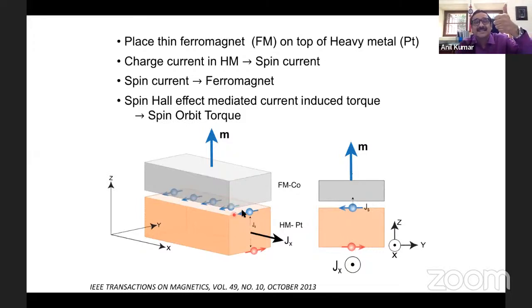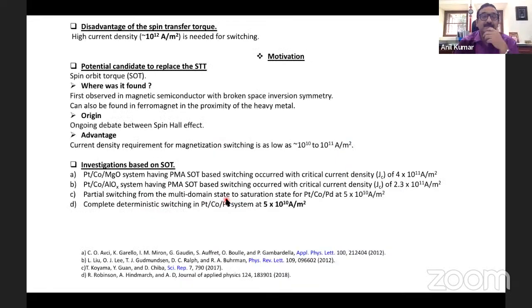This spin Hall effect is coming due to spin orbit interaction in the heavy metal, because the heavier the material, the higher the spin orbit interaction. Because it originates from the spin orbit interaction, this torque is called spin orbit torque, right? So now let me set the motivation. For the spin transfer torque, you need 10 to the power 12 ampere per meter square as a switching current, and you want to develop materials that can be switched with much lower electrical current.